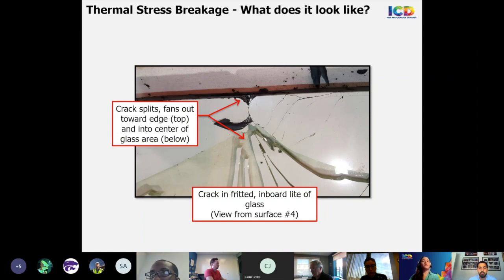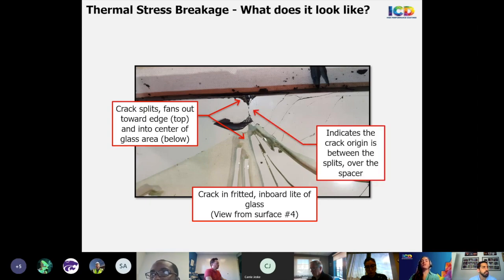And this tells us that the crack origin is somewhere in this region between the two fans, which is significant because cracks in annealed glass typically begin right at the edge of the glass. And in this case, the crack is clearly beginning inward away from the edge.